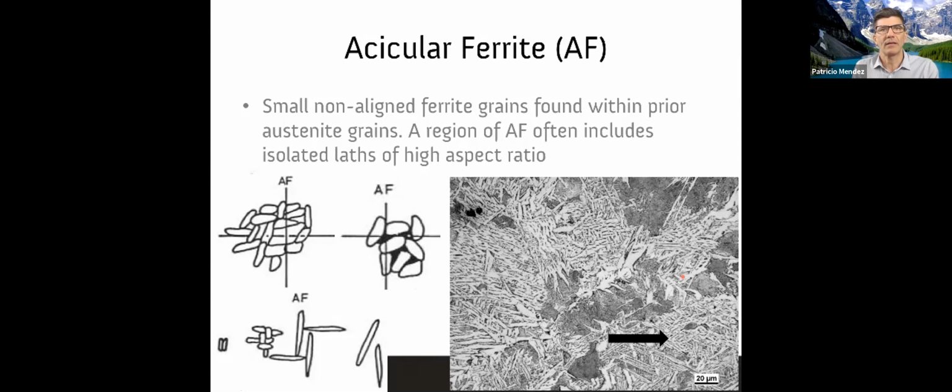And the reason we see acicular ferrite in the weld metal is because we intentionally nucleate it, typically with titanium oxide. And that's why filler wire has some amount of titanium that base metal seldom has, and also why we don't want to have zero oxygen in our weld, because we need some amount of oxygen to oxidize that titanium. And when we nucleate the acicular ferrite, it looks like this.